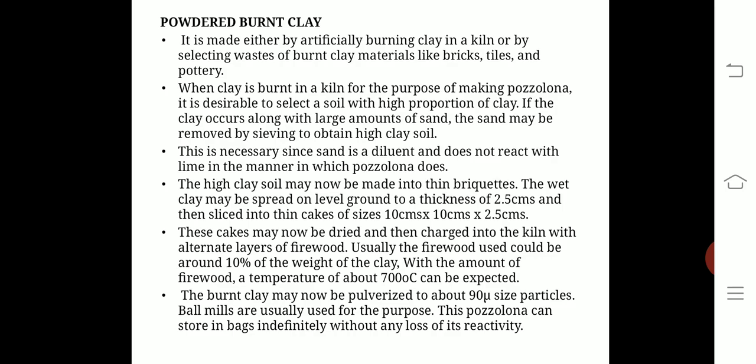The high clay soil may now be made into thin briquettes. The wet clay may be spread on level ground to a thickness of about 2.5 centimeters and sliced into thin cakes of size 10 by 10 centimeters, maintaining the 2.5 cm thickness. These cakes are dried and charged into the kiln with alternate layers of firewood, similar to lime production. Firewood used is about 10 percent of the weight of clay, achieving a temperature of about 700 degrees centigrade. The burnt clay is then pulverized to about 90 micron sieve size using ball mills and can be stored in bags indefinitely without loss of reactivity.